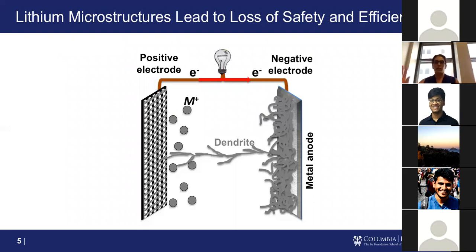So what is actually going on whenever you have these scenarios of thermal runaway, and how do we start to study this a little bit better, and what does this mean in a real life scenario? So this is, again, just showing a schematic of a lithium ion battery. Whenever you do something like charge a battery too fast, I told you that you can get lithium metal plating on the anode side of the battery instead of intercalating into that inner layer space. So this is just a cartoon showing lithium metal that's deposited on the surface of an anode. And lithium metal, whenever it's depositing, tends to grow in these wiry dendrite-like structures that I'm showing here.